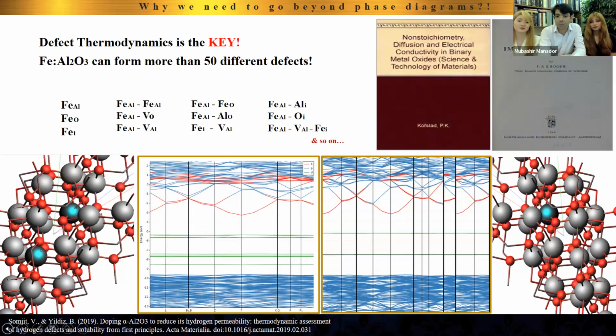For example, take into consideration if there are two iron atoms inside the alumina crystal, adjacent, or even one iron, and so the band structures that they form are completely different from one another. Therefore, their optical properties are absolutely different. That means if we could somehow understand the experimental conditions which give rise to a particular defect, based on the heat treatment conditions, then we would be able to know the kind of Raman peaks, the kind of FTIR peaks, and so on, that each defect would produce.